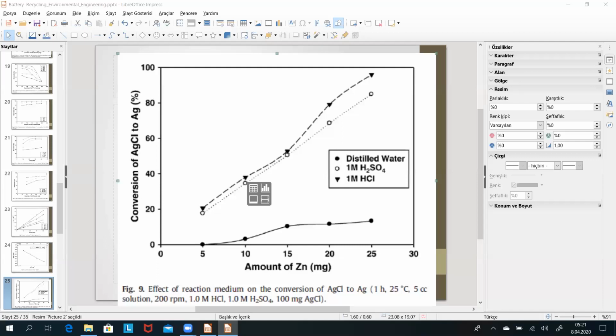This powder can be used directly in various applications, including the production of silver nitrate, which is used in antibacterial and pharmacological applications, or in the production of silver cyanide, which is the main component of silver plating baths in jewelry and as an alloying element. Well, let's come to the zinc nitrate solution. Zinc nitrate solution from the initial leaching process and zinc chloride solution from the replacement reaction can be put together for zinc precipitation with sodium hydroxide. The proposed process avoids environmental problems and allows for the non-hazardous hydrometallurgical recovery of valuable silver from silver oxide button cells.